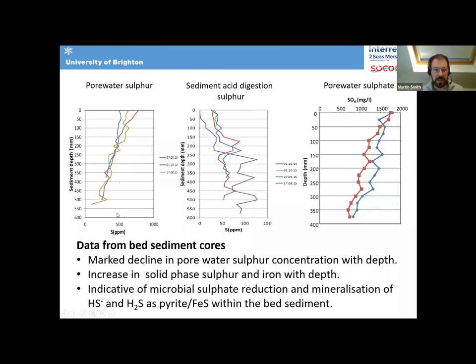And there's nothing new about these profiles. They've been seen in many, many sites worldwide, but the pore water sulfur goes down, the solid phase sulfur goes up, and we can attribute the reduction in the total pore water sulfur to sulfate reduction and the formation of pyrite. So there's nothing unusual there, but it just tells us that the sulfate reducing bacteria are present in the bed sediment.